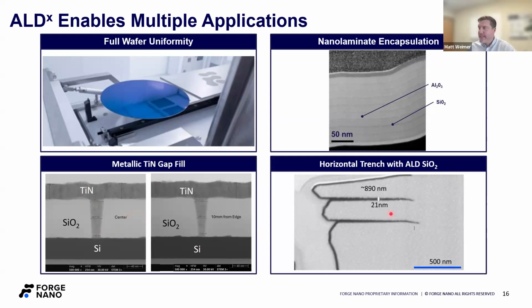So quite fast. And then, finally, the other question we get a lot is with the surface catalysis, with the CRISP process, is that still ALD? Is it still conformal? So this is a silica CRISP film coating in black here. These are horizontal features that are about 35, 36 to 1. And the ALD film coats this conformally. It's harder to see here, but it's actually performing gap fill as well. We know that these features were coated because they were stress tested and passed with flying colors.